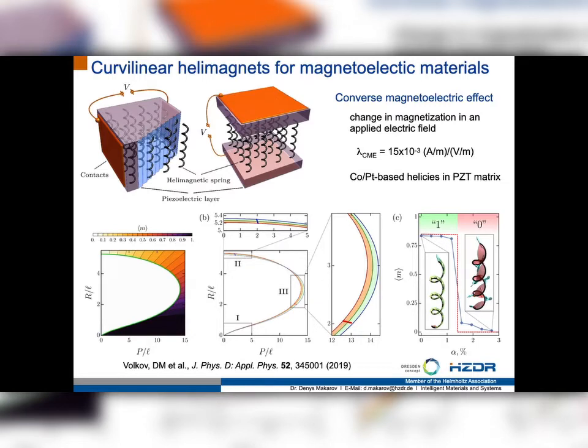What is important about this, like an added value which you have, is that it's an artificial magnetoelectric material where the magnetic state can be controlled by applying electrical voltage to the piezoelectric matrix. And what is important here is that the change of magnetization is so large that you can get a very large converse magnetoelectric effect in this artificial magnetoelectric material, which is about an order of magnitude larger than what you can get in the best laminates which you have from, let's say, magnetostrictive and piezoelectric materials.